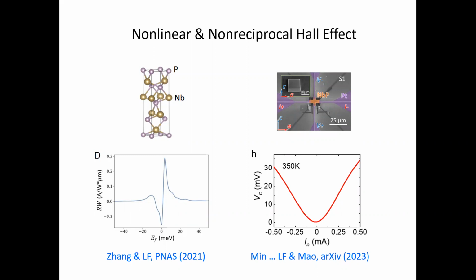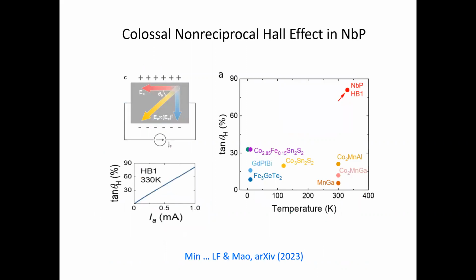So now indeed, you see this is all raw data. And you see the quadratic type of IV curve, okay? One way to see how big this effect is is to look at the Hall angle, okay? When you pass the current, then when the Hall transverse voltage develops, the ratio of the transverse and longitudinal voltage defines a so-called Hall angle.